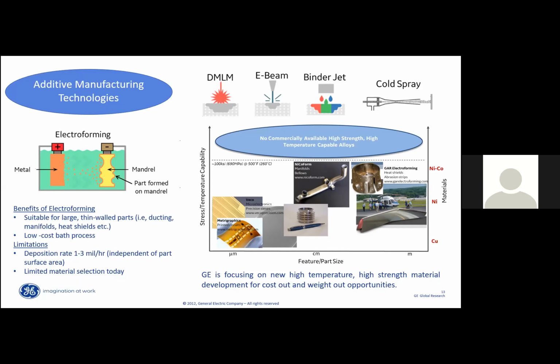The deposition rate is low. So if you're used to higher build rates with additive manufacturing, our dep rate with electroforming is typically 1 to 3 mils an hour, but that's independent of the part surface area, right? So it would take you the same amount of time to electroform a paper clip or a helicopter heat shield.